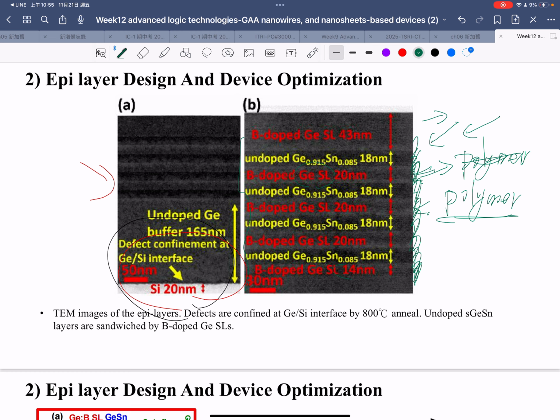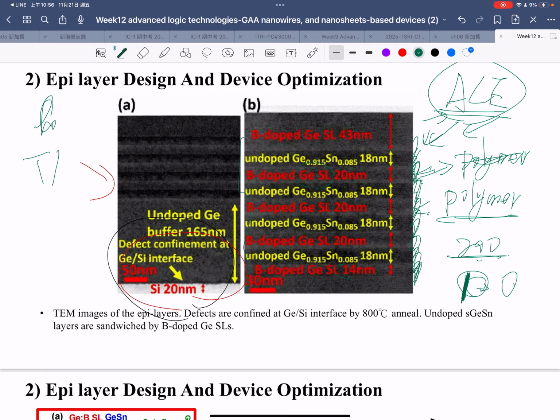So we have tested several times, and sometimes the etching selectivity is over 200. Sometimes no etching. The etching selectivity is very close to 1. No, actually 0. Almost no etching. So we have discussed such an embarrassing situation with the engineer. The engineer said that actually at the interlock they use high temperature, maybe 300 degrees Celsius to 400 degrees Celsius, to remove the polymer. But actually it's not easy.